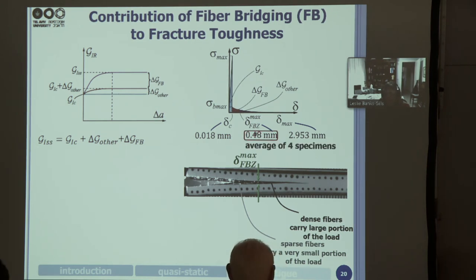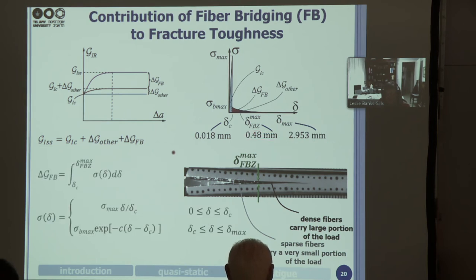We obtain the delta FBZ max from the average of four specimens. We actually measure it using the images that we've captured. Then to get delta fiber bridging, we integrate the traction separation region, this red region, between delta C and delta FBZ max. And this is the equation that we substitute in here.